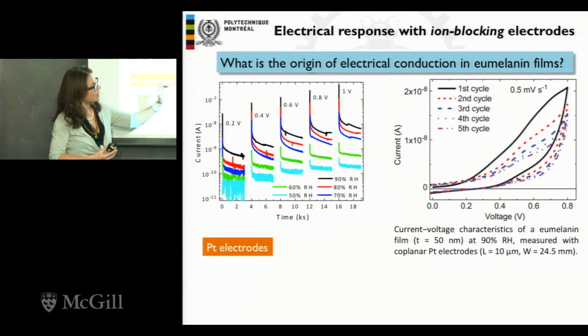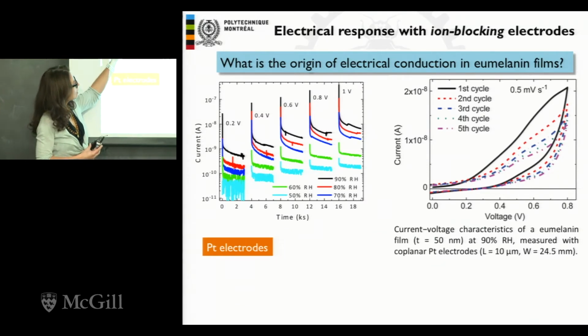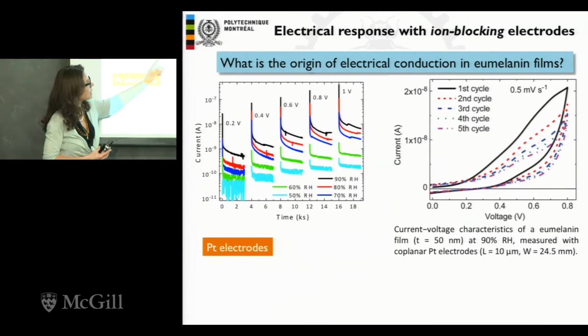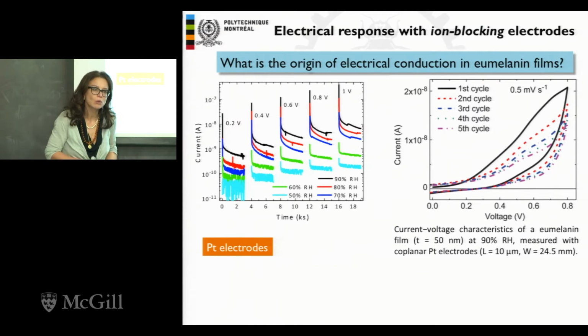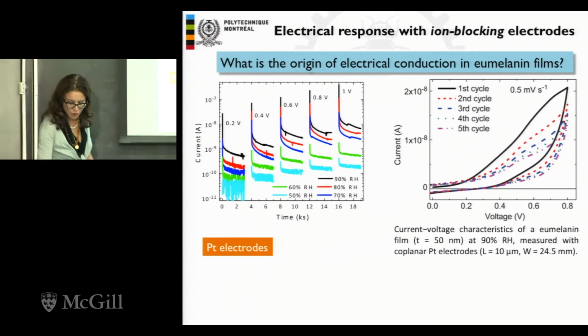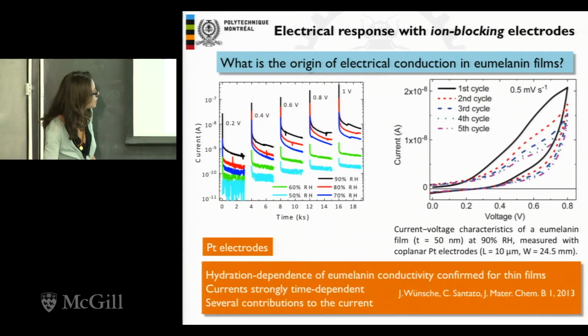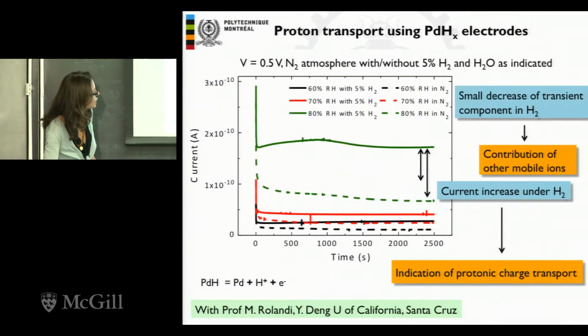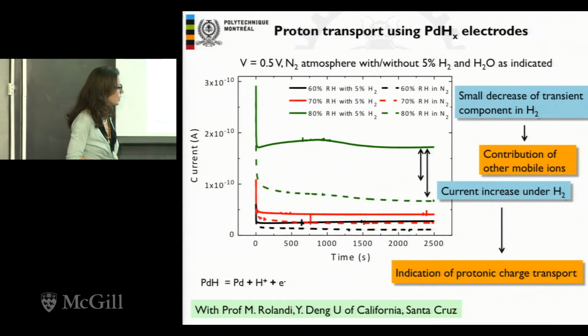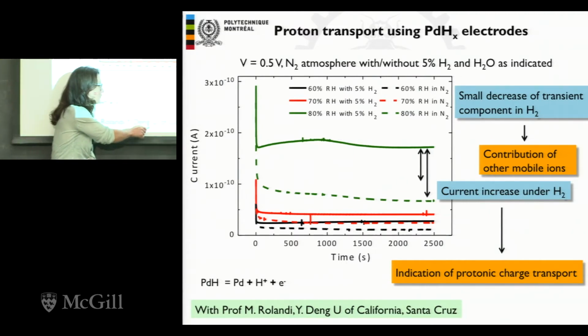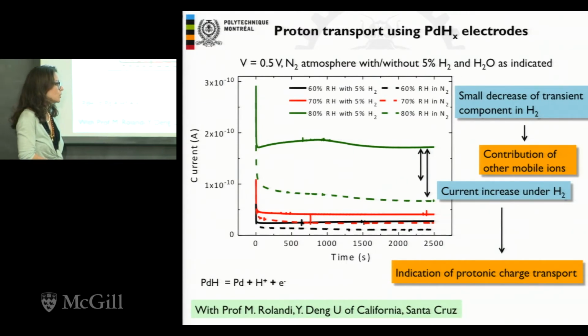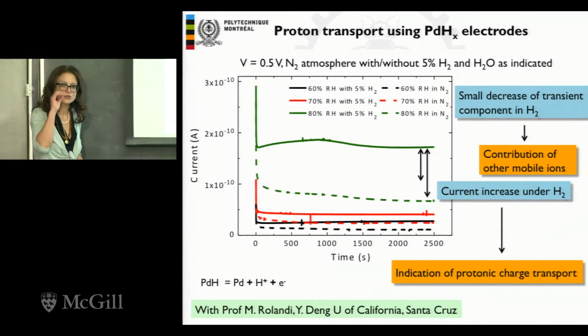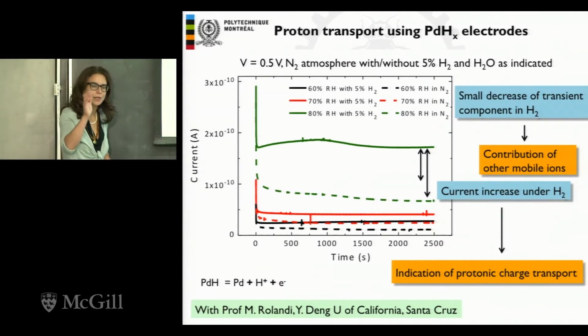We measured the current versus time at different degrees of relative humidity in the atmosphere of our melanin, and somehow we confirmed the hydration-dependent conductivity. We went further in this, collaborating with a really interesting group now at the University of California in Santa Cruz. This could be of interest for you. Maybe Noemi, you know it already.